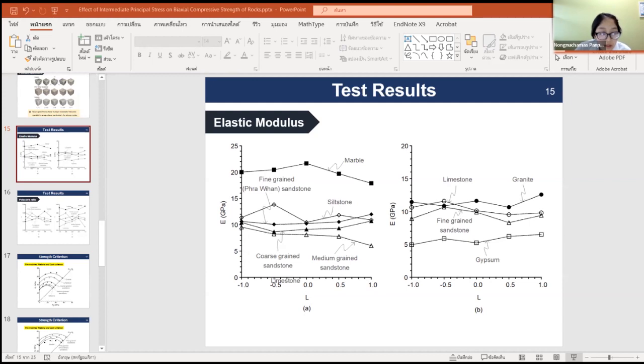The predictive capability of the proposed strength criteria for the 9 tested rocks is determined using the mean misfit as an indicator. The low mean misfit values of our tested rocks are shown in this table, suggesting that the modified Weibull and Cook criteria can describe the rock strength under biaxial conditions. About Kirsch solutions, for analysis of stress around a circular hole in a finite plate, it's proposed to demonstrate the effects of intermediate principal stress on the stability of a deep tunnel. This assumes that rock surrounding the cylindrical tunnel behaves as a linearly elastic material. The equation for solving this problem is widely used and is commonly referred to as Kirsch solutions.